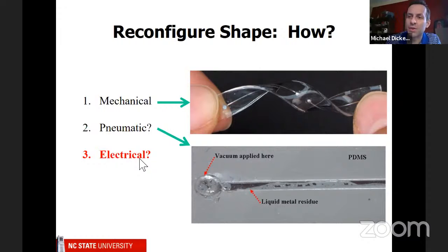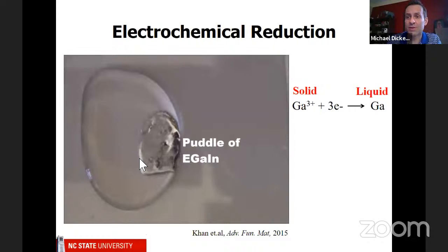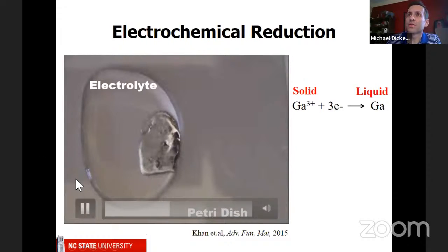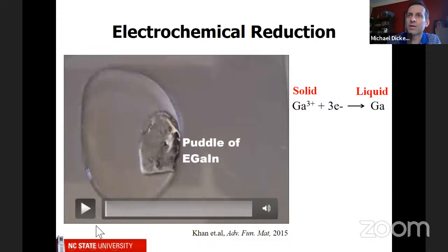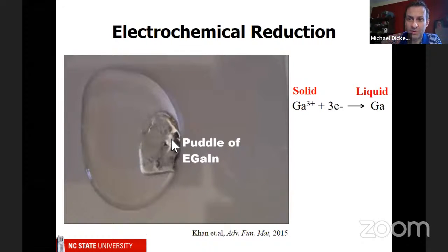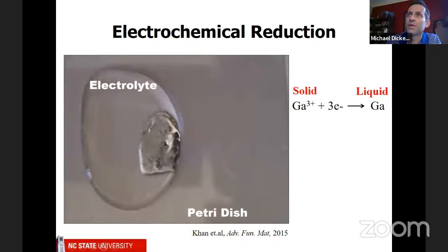All right, so how do you do this? Well, we actually do this using electrochemistry. In this video, let me pause it for just one second. What you're looking at is a puddle of the liquid metal, and it's sitting in salt water. Right now it has an oxide layer on the surface, but it's very thin. If we apply a reducing potential, so we give it some electrons, we can convert the oxide, which is a solid, into gallium, which is a liquid. So here we go. We're going to take two electrodes and apply about -1 volt.